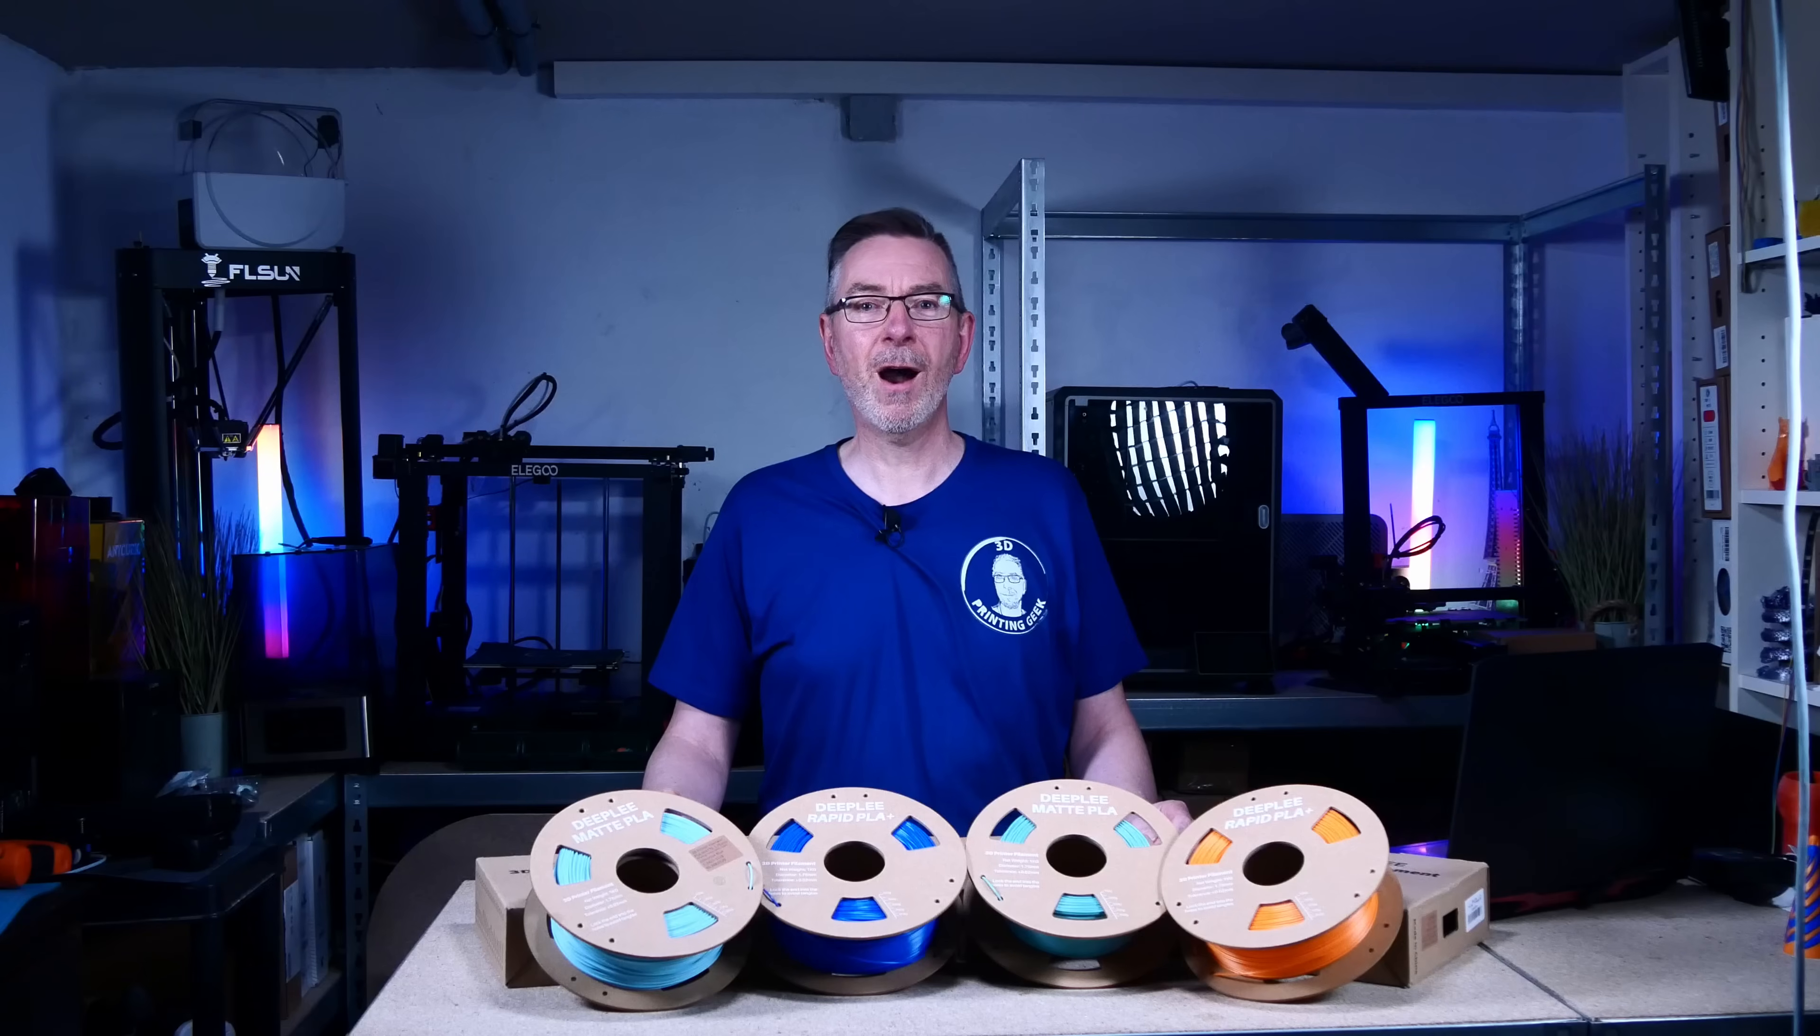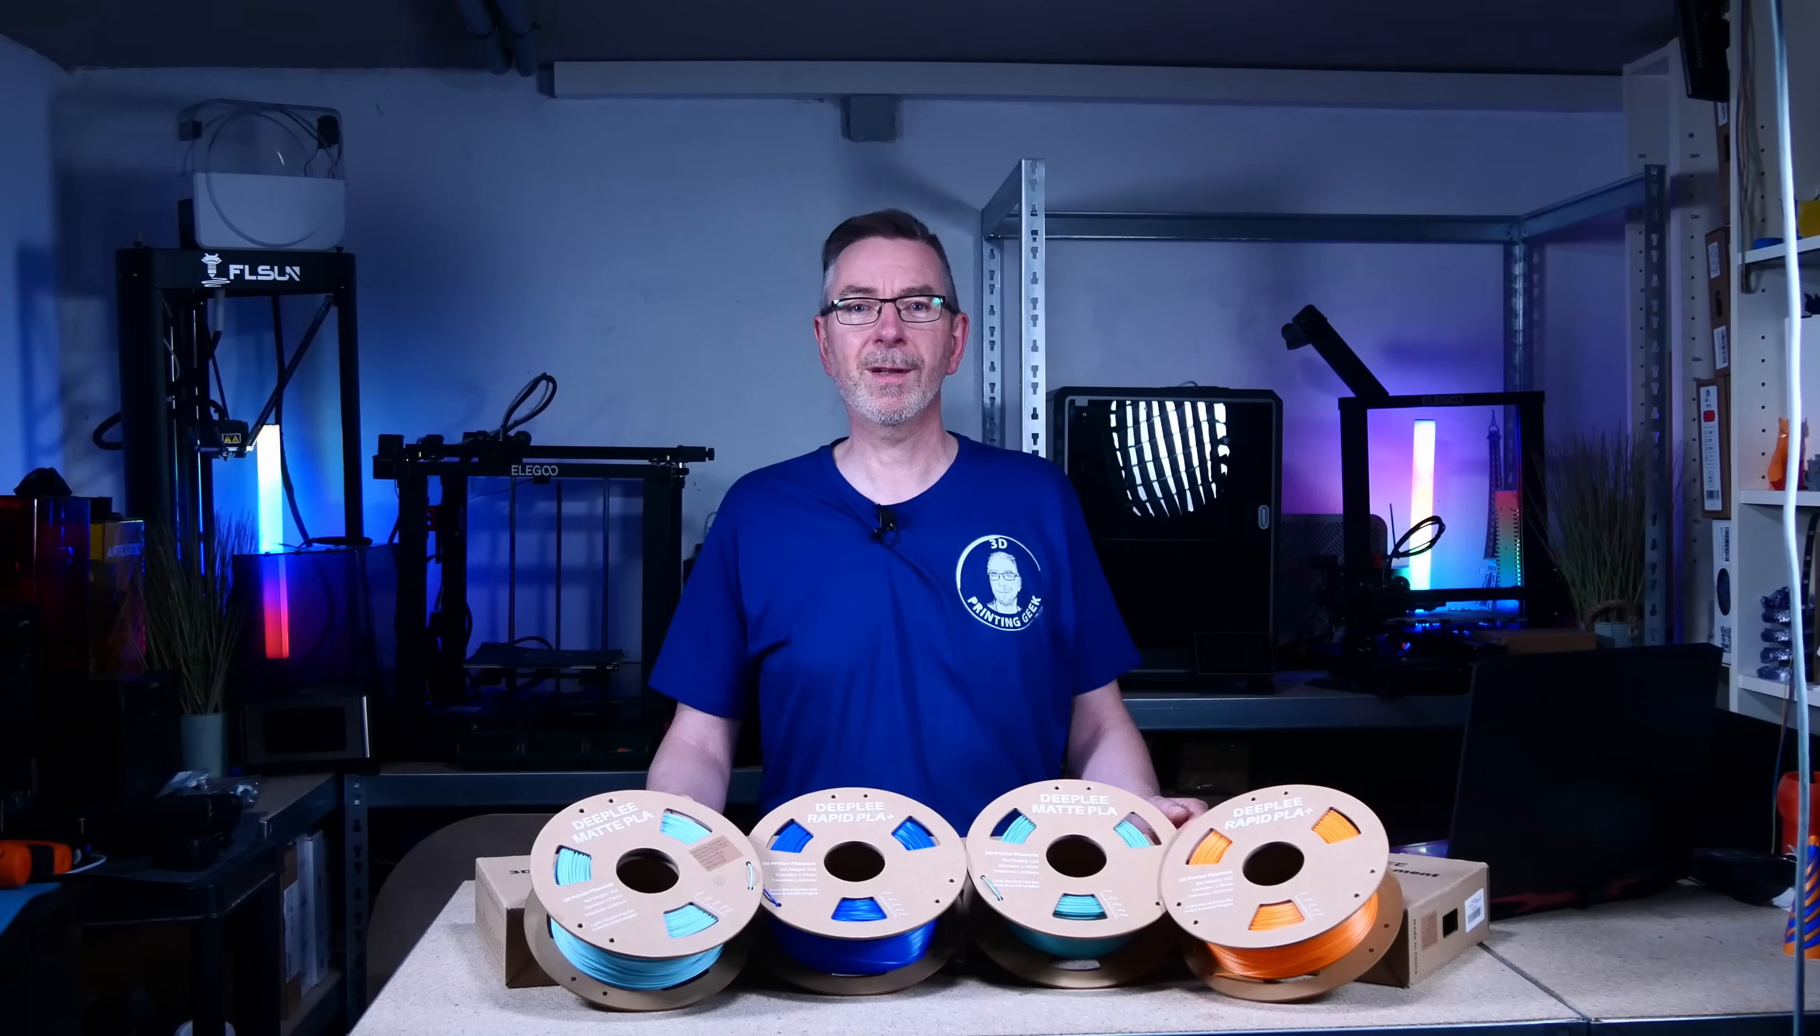The standing samples had only about one third of the strength and broke cleanly across the layers. Next, let's check how good the filaments handled torque. I was prepared for breaking my samples, but the test revealed an unexpected twist. The samples for the torque test were printed using 100% infill, in standing and flat orientation. Then I fixed the specimens in the vise and tried to apply torque evenly until they broke or a full turn was made, whichever happened first. I think the test setup I chose is not good for getting a clear picture of it. Nevertheless, I don't want to withhold the results from you. Unsurprisingly, the samples printed flat are stronger than the standing ones, whereas in the impact test the weakness comes from the layer bonding and relies more on the chosen printing parameters. I wasn't able to break the flat printed samples, they just twisted and stayed that way. Let me know in the comments if you know a more reliable way to do a torque test.